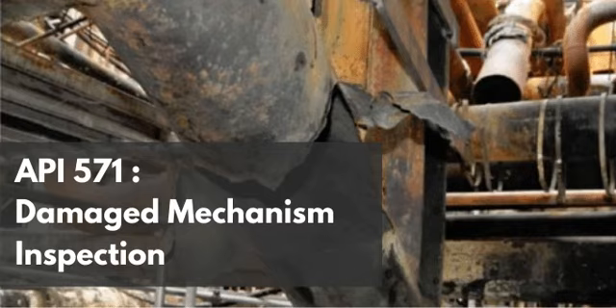That small amount of ferrite acts as a sponge for impurities and essentially disrupts the straight grain boundaries, completely preventing the hot cracking. So we intentionally engineer ferrite into an otherwise totally immune austenitic piping system. Yes. It's like a metallurgical pharmaceutical. Oh, that's a good way to put it.